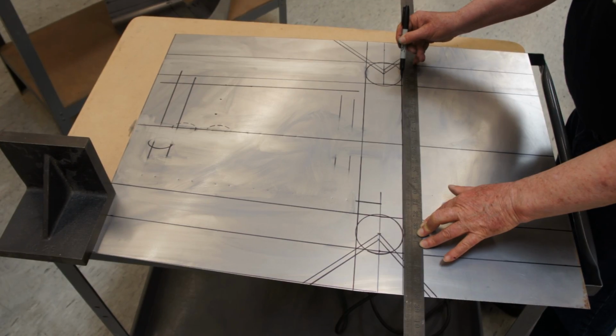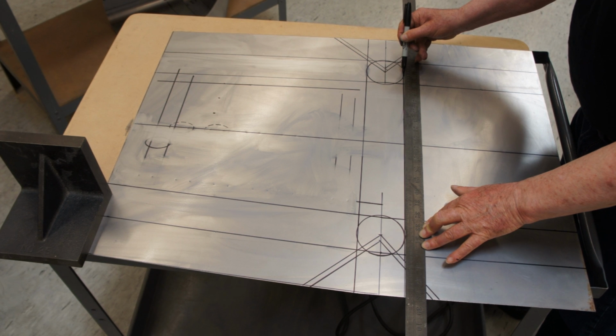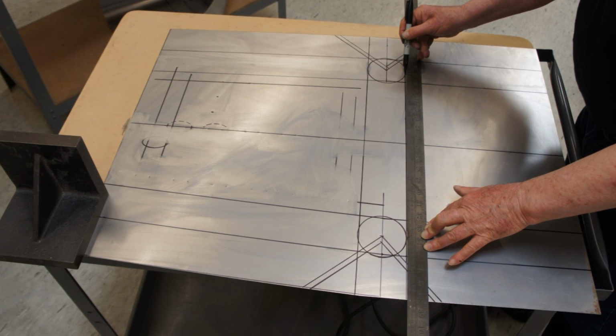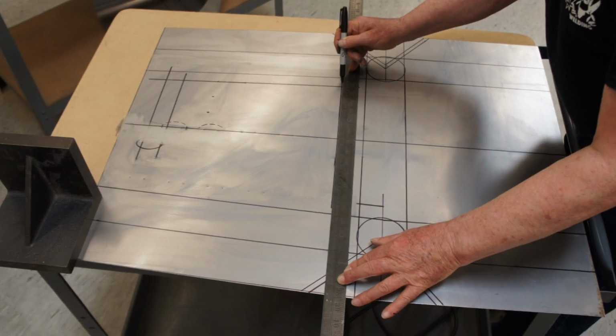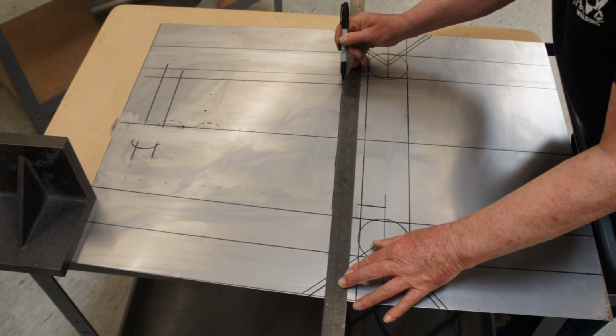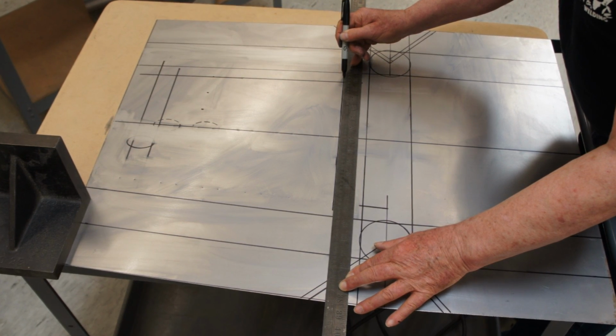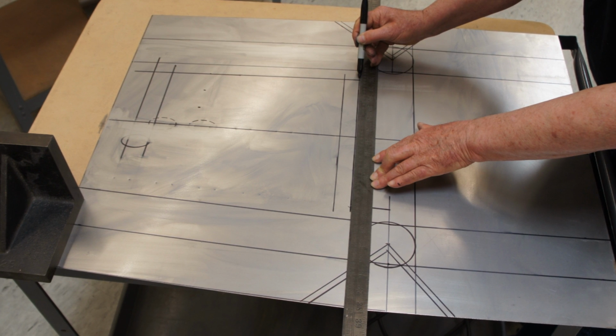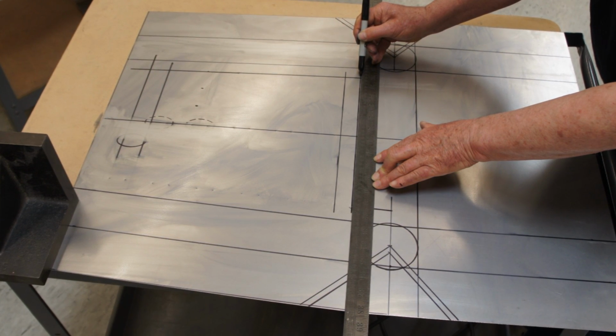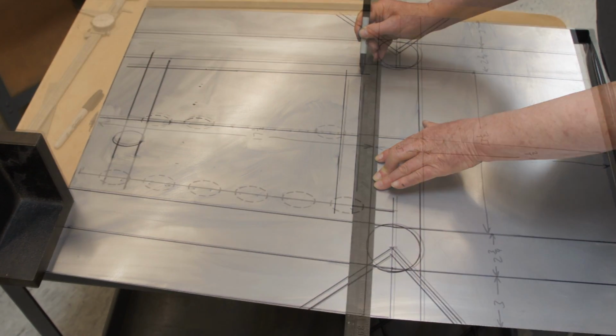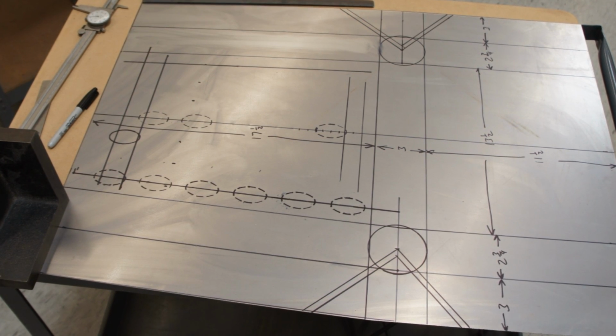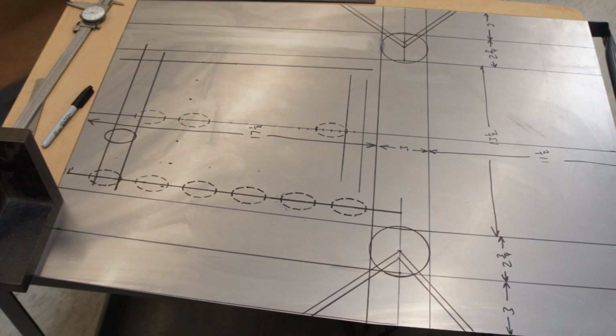I'm using a felt tip marker to lay out the cuts and the hole locations on a sheet of cold rolled steel. My goal is to make the seat 18 inches wide, or about 46 centimeters. Since each bend shrinks 4.5 inches, I need to add 9 inches to my blank, so the width before bending will be 27 inches, or about 69 centimeters.